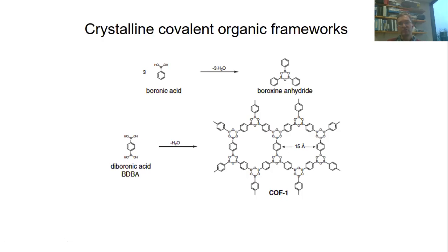Now, if you choose the reaction conditions right, you can decide or tune how much of that water remains in the reaction equilibrium. That you can tune by choosing the relative volume of your liquid phase that contains the solvent and the reactants relative to the gaseous phase.